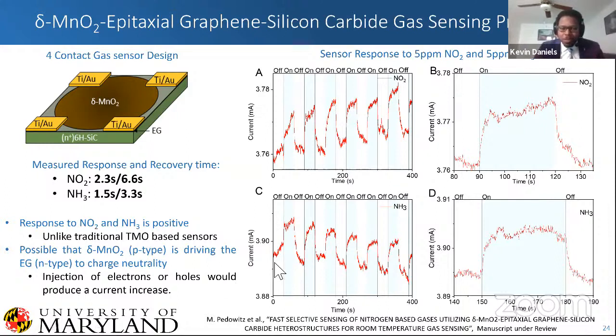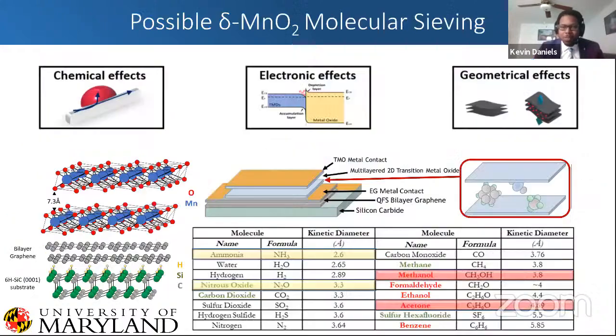And it's also interesting to note that we exposed this to isopropanol and methanol, similar to the molybdenum disulfide sample, and there was absolutely no response, which is very, very interesting as far as selectivity goes, because graphene would light up immediately if it was exposed to those gases. And so there's 3 effects that we take a look at: the chemical effects, the electronic effects, and the geometrical effects. Now, as I showed before, manganese dioxide has a pretty large interlayer spacing of 7.3 angstroms.